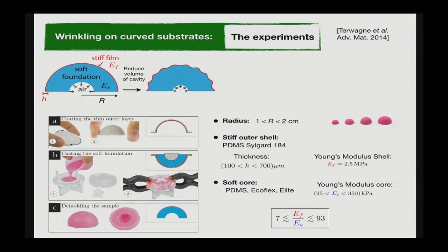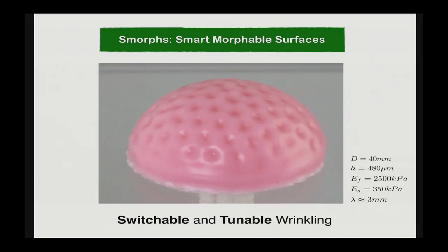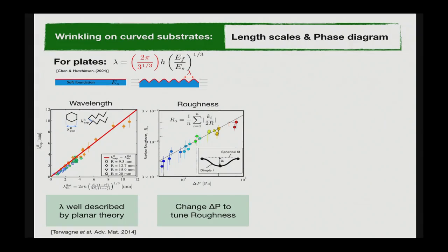Anyway, so knowing how to make these things, we can now tune parameters for the shell and for the core. We work over a range of stiffnesses over a factor of about 100. And when we depressurize these samples, they actively switch instantaneously, so this is not through swelling, it's through pneumatics, so they're fast, and we can excite these dimple patterns. And this is where we saw the analogy, there might be something here that connects to golf balls. But before we get there, let me briefly tell you how we can tune parameters in order to get different patterns.